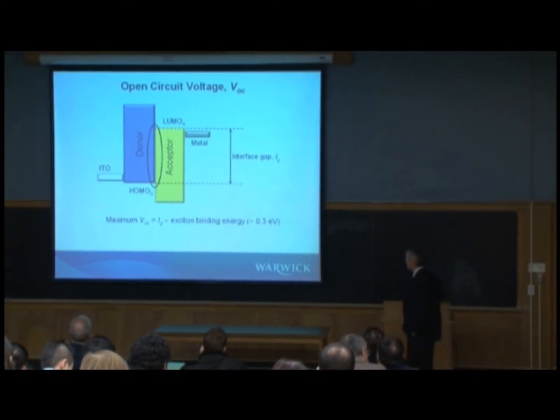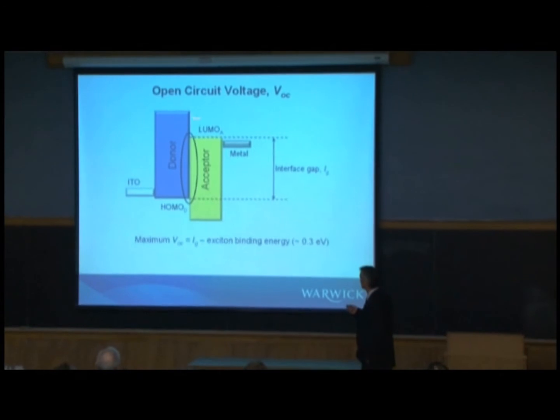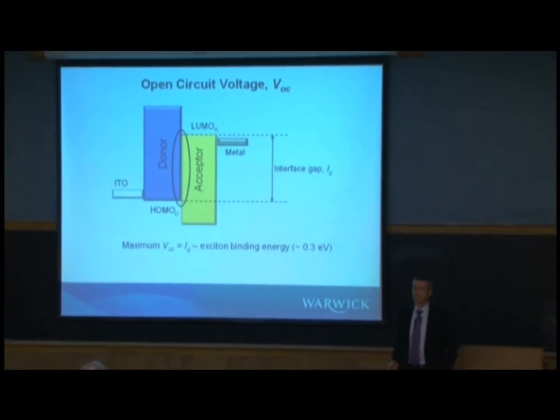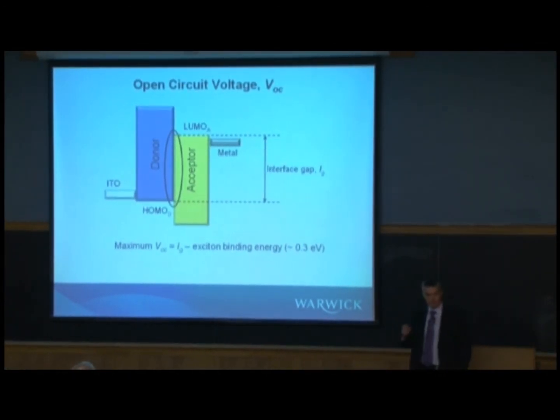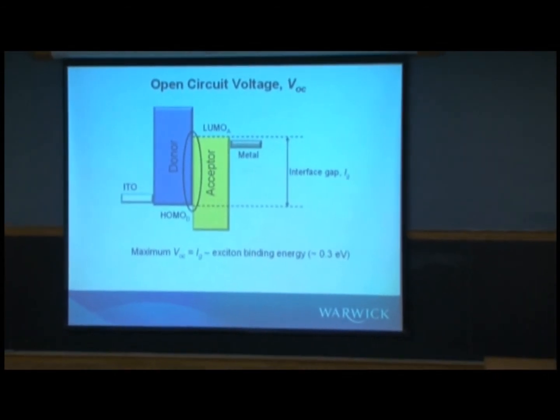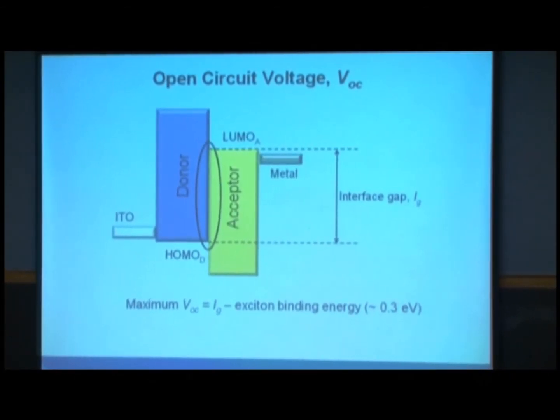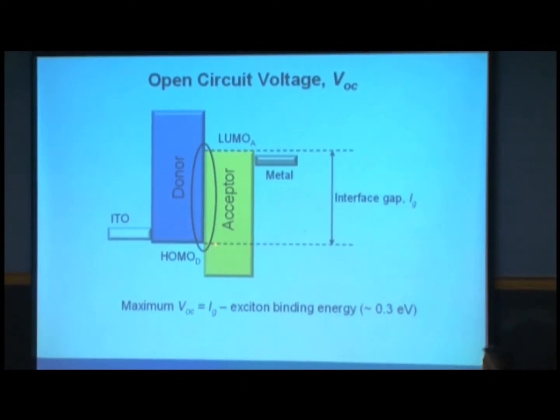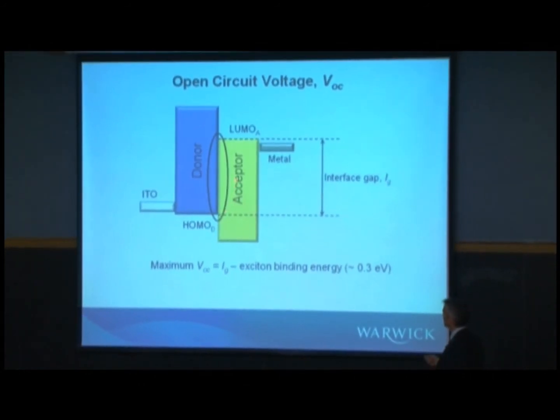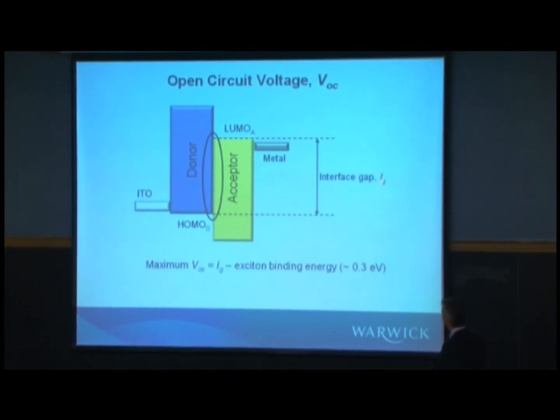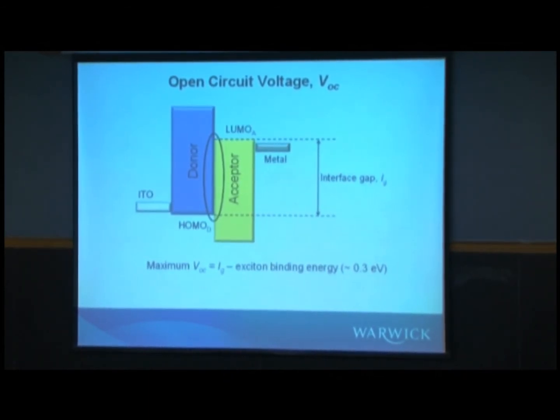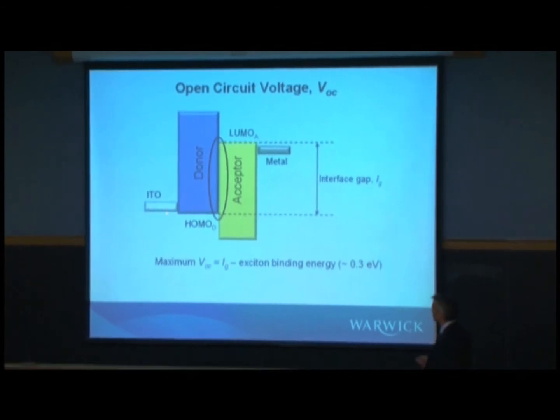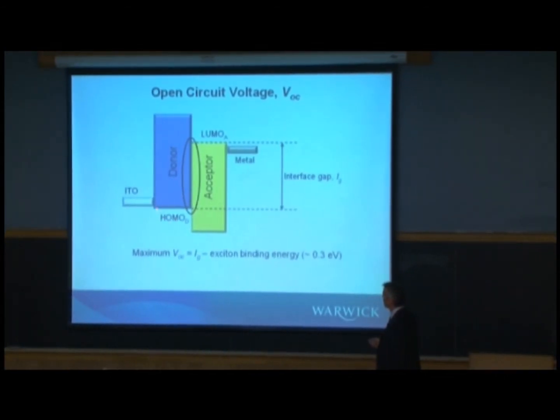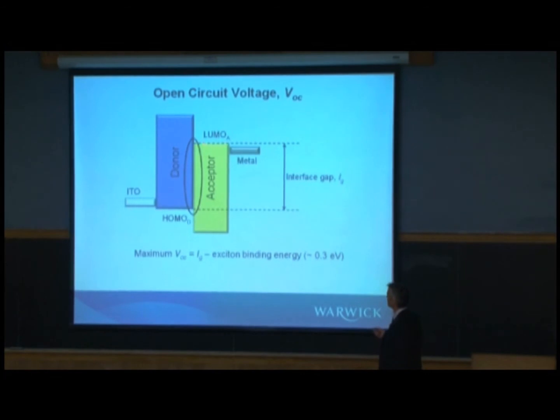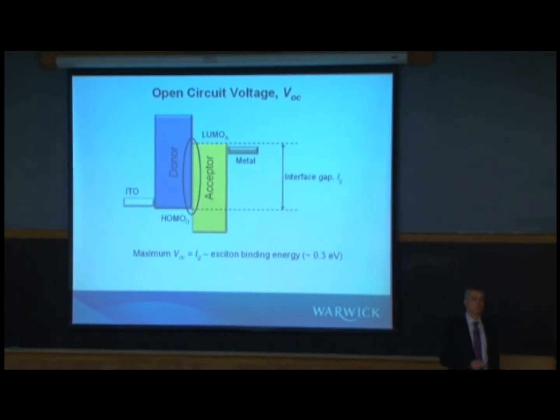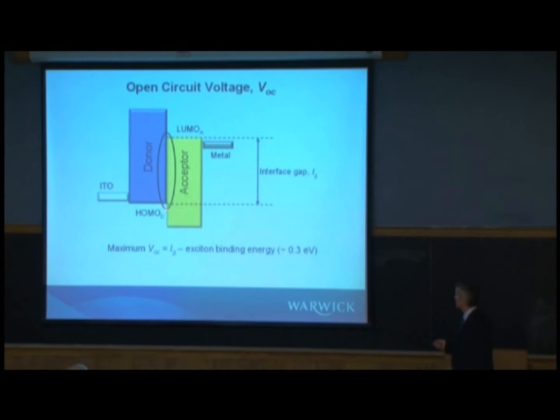So, open circuit voltage. This is our nice schematic of a donor acceptor heterojunction, with the interface in between. There's been some debate for several years about the origin of that voltage, but in essence it's related to the size of this energy gap, this interface gap energy, Ig, which is the difference in energy between the highest occupied molecular orbital of the donor, the HOMO of the donor, and the lowest unoccupied molecular orbital of the acceptor, the LUMO of the acceptor. And that defines the interface gap.